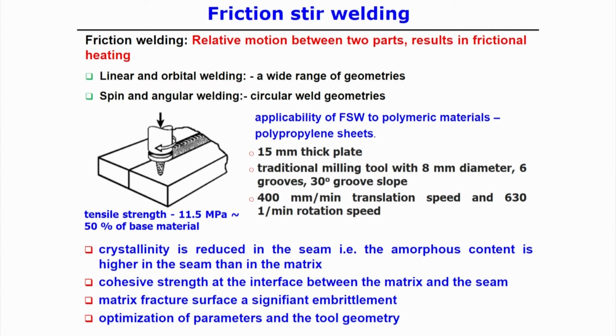But for the friction stir welding process for polymeric material, we can see the application with polypropylene sheets. Here two plastic sheets are in contact, and in between we use a tool. The tool's rotation generates heat, and at the same time there is a linear movement of the rotating tool along the welding direction. So, this is the principle of the friction stir welding process. Using this process, it was tried on polypropylene sheets for joining of the two materials.